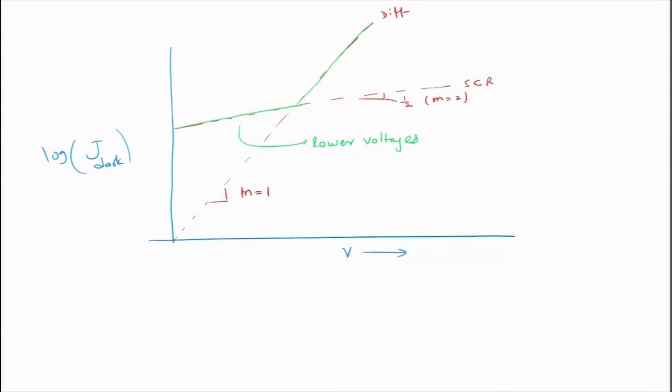However, what is likely to happen if carrier lifetime decreases? If carrier lifetime decreases, the space charge recombination will become more and more. So, if the carrier recombination increases, this curve tends to shift up or down; it will shift in this direction. So, if your carrier recombination increases, it tends to go up.